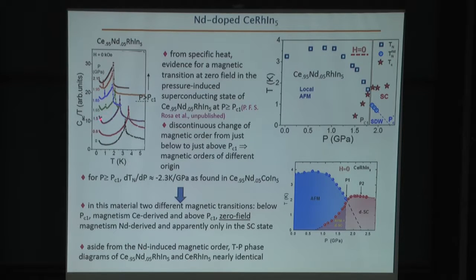And then there is a hint of superconductivity that develops in the magnetic state that becomes more pronounced as we increase pressure a little bit more. But once we increase pressure a little bit higher, evidence for this magnetic transition disappears. Instead, this large anomaly here now is the superconducting anomaly, and here's a small anomaly that we associate with antiferromagnetic order.